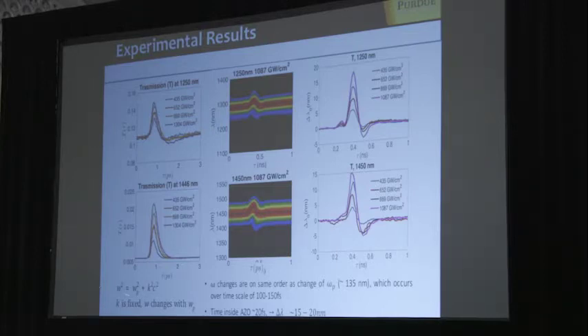Actually, to understand this, you should look at this dispersion relation. Since I'm pointing out for this time refraction, wave vector is conserved, it means that the frequency will change as much as the plasma frequency changes. And as I pointed out, for transparent conducting oxides, you could change the plasma frequency quite dramatically if you look at the ENZ point. So our calculation shows it's actually 135 nanometers. However, since our layer is relatively thin and light spends only 20 femtosecond there, and to develop this shift it takes 100 to 150 femtosecond, the shift we observe is on the scale of 15 to 20 nanometers. Clearly still enough to obtain all this very interesting effect.